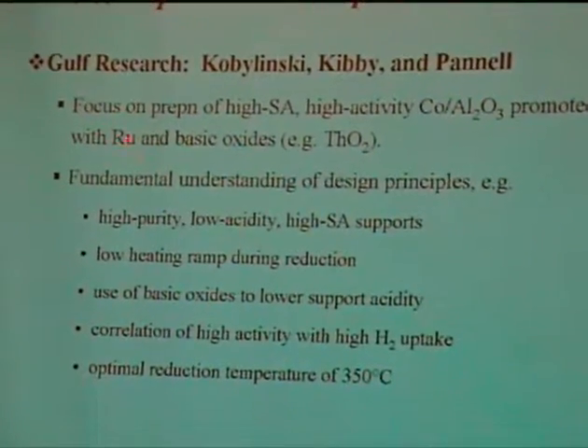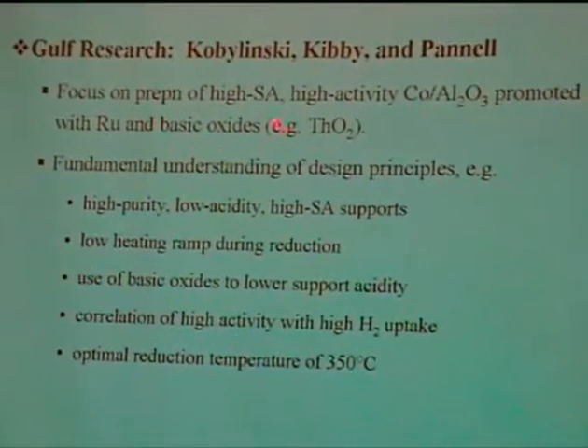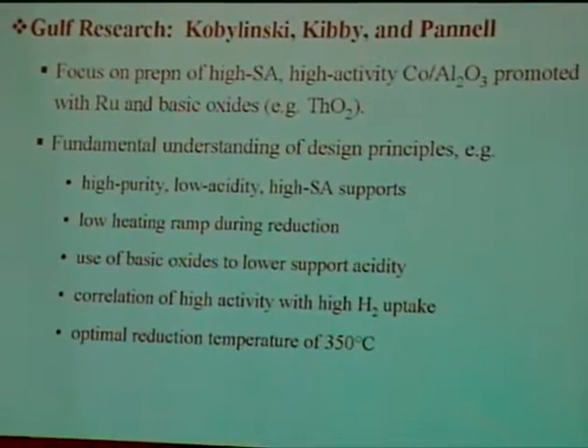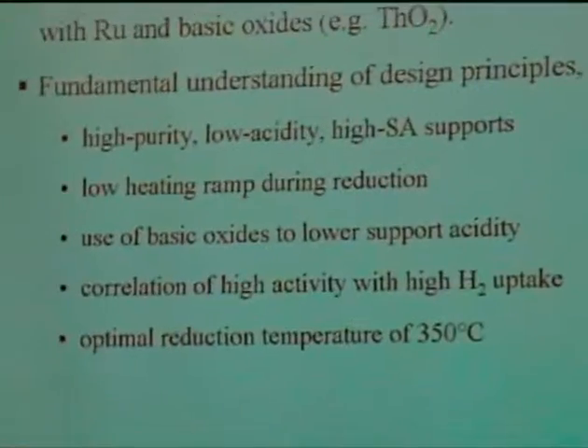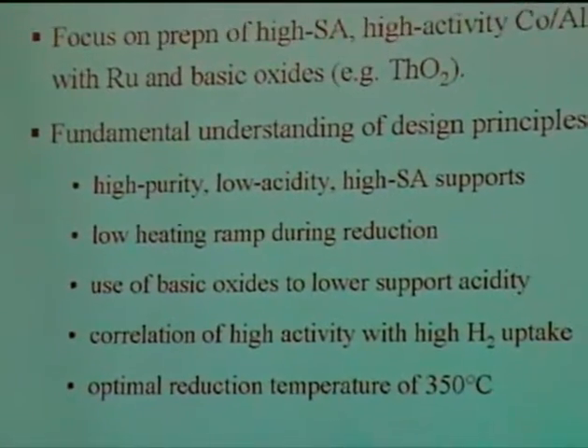They initiated work on ruthenium as a promoter and the use of basic oxides. As you read their patents, you find that they had a pretty good fundamental understanding of several design principles, which they describe very well in their patents. This includes high purity, high acidity, low acidity, high surface area supports, which prevent or minimize the formation of methane, but maximize the formation of an activity of your catalyst.